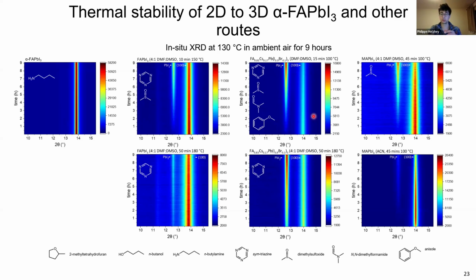So we exposed the films to 130 degrees in air and measured it for 9 hours. And then essentially monitored the 100 peak position over time. So here on the x-axis, you see the 2 theta degree angle, and here you see the 100 peak position. And then on the y-axis, you have the time. And then the intensity shows the diffraction intensity of the XRD.